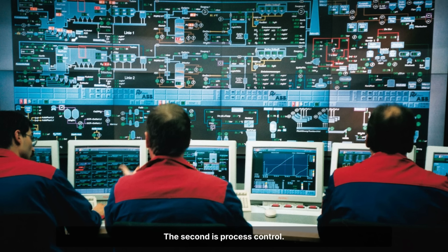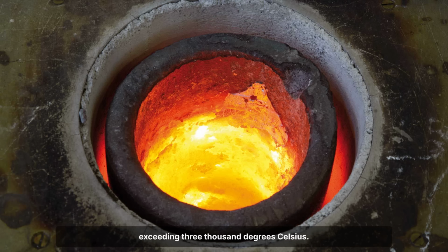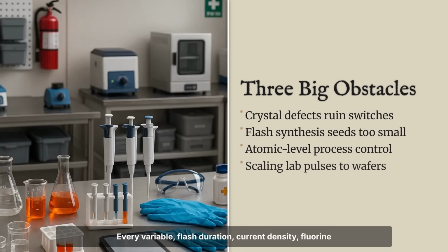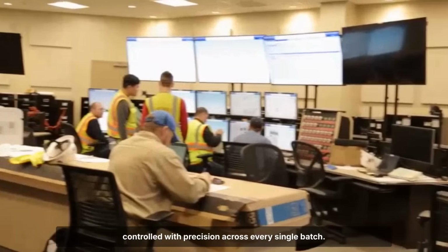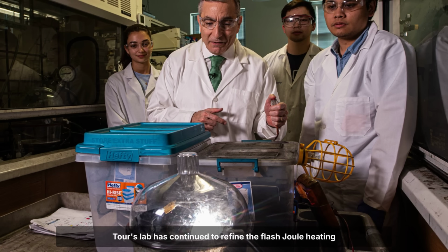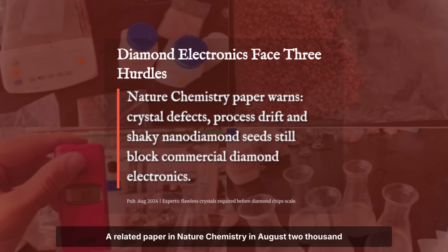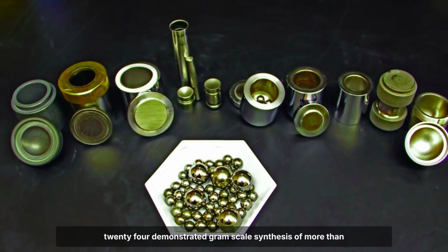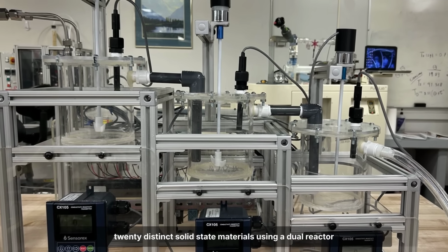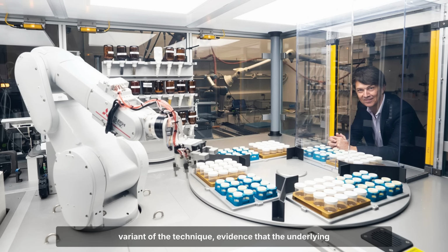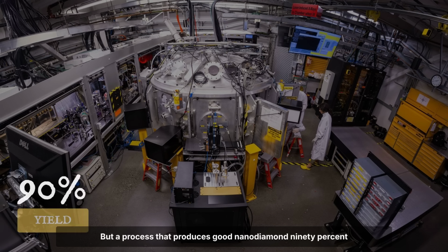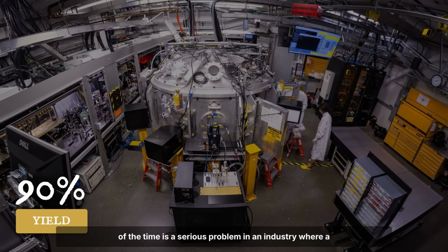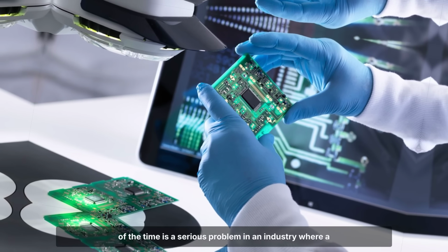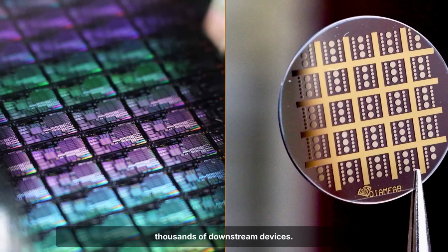The second is process control. The flash happens in under a second at temperatures exceeding 3,000 degrees Celsius. Every variable, flash duration, current density, fluorine concentration, feedstock composition, cooling rate, must be controlled with precision across every single batch. Tour's lab has continued to refine the flash Joule heating platform. A related paper in Nature Chemistry in August 2024 demonstrated gram-scale synthesis of more than 20 distinct solid-state materials using a dual reactor variant of the technique, evidence that the underlying process is becoming more controllable and generalizable. But a process that produces good nanodiamond 90% of the time is a serious problem in an industry where a single contaminated batch can propagate defects through thousands of downstream devices.